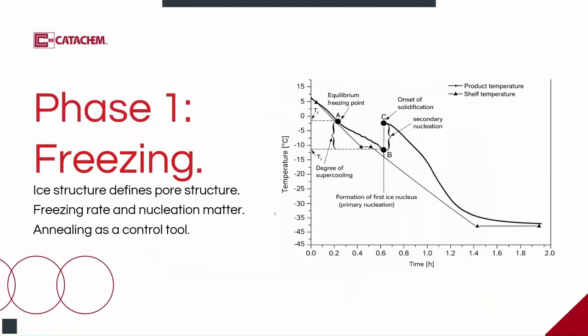Phase 1 is freezing, and in many ways it determines everything that follows. Freezing creates the ice structure, and the ice structure becomes your pore network after sublimation. Larger, more open ice crystals generally produce larger pores, and less resistance to vapor flow, which can shorten primary drying and improve uniformity. But freezing too slowly may create phase separation or destabilize some active ingredients. Freezing too fast can create very fine ice crystals, a reduction in pore size with less space for water vapor to escape, and therefore slower drying.